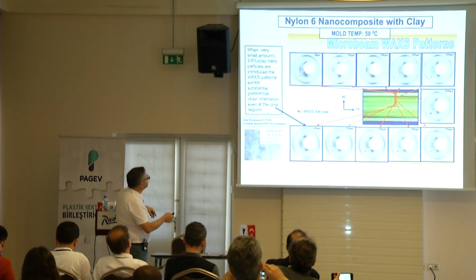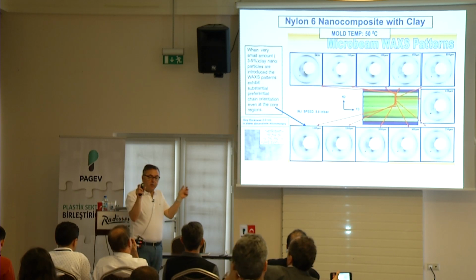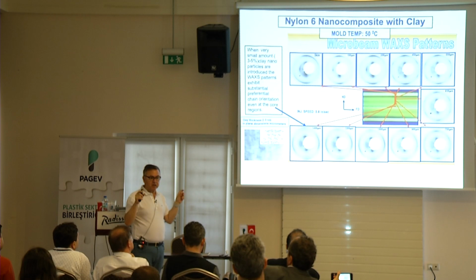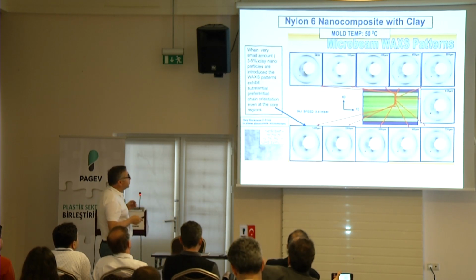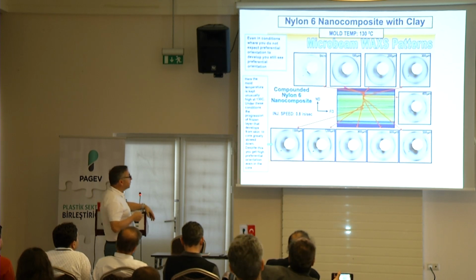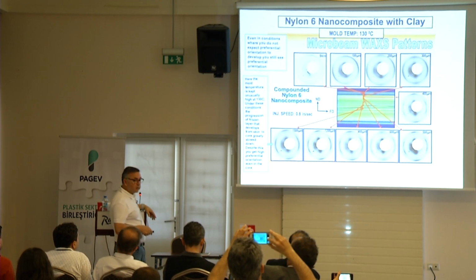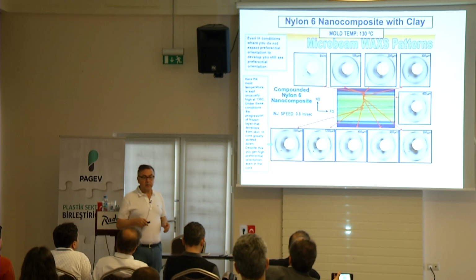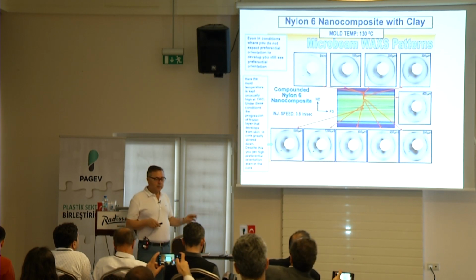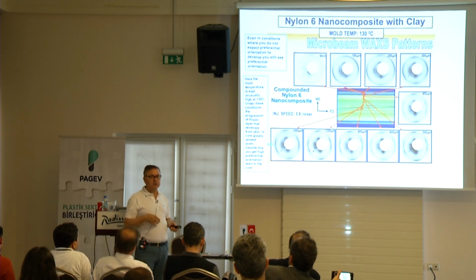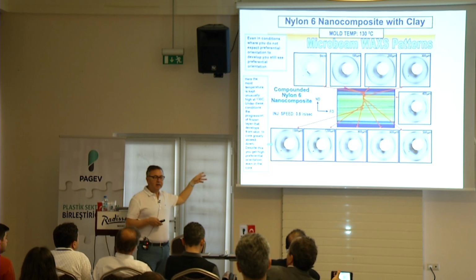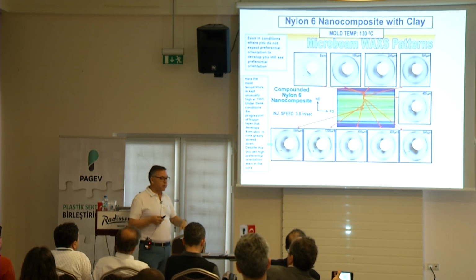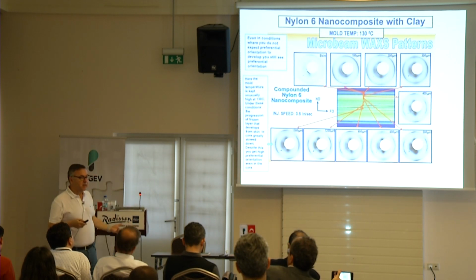Now this was a mold temperature of 50 degrees, so we are creating a reasonably large solid skin during the injection process. We said, okay, what if we go to 130 degrees mold temperature, pretty high for nylon, just 100 degrees below the melting point? You see the same thing. So it doesn't matter. You can get the orientation dramatically by simply adding what they call magical dust. Many people use nanocomposites for barrier applications and so on. I think the hidden value of nanocomposites is as processing aids. It will make nylons orient dramatically, and then the properties would obviously be dramatically influenced. That's not possible any other way.